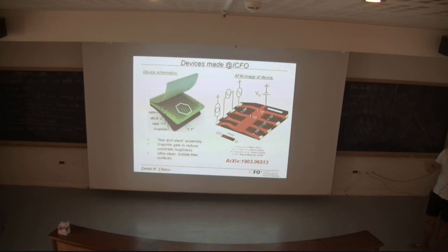So whenever we, in our field, say we do doping, that means we apply a gate voltage and we just change electrostatically the carrier density concentration. So this is a typical AFM image of our device. The devices are not very large. This bar here is 5 micrometers. So usually our devices are at best 10 micrometers long and maybe 2 micrometers wide.